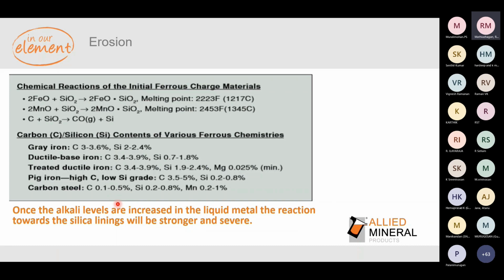This slide talks about the reaction of the initial charge over the silica lining. For example, a lot of iron oxide reduces the melting point of silica to 1217 degrees Celsius. MnO present in the metal reduces the silica melting point to a range of 1345 degrees Celsius, because normally silica melts at 1710 degrees Celsius. So try to avoid all these things, and we'll be talking further on this. Also, you can note the carbon silicon content of various ferrous chemistry in this slide. This will help us keep a check on the charging practice during the sintering and regular operations. Also keep a watch on the alkali levels. When they increase, they also have a strong effect over the silica working linings.